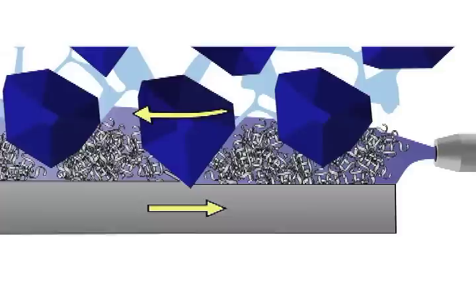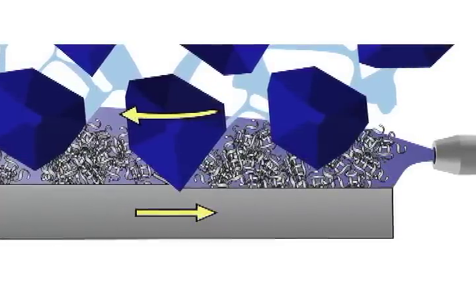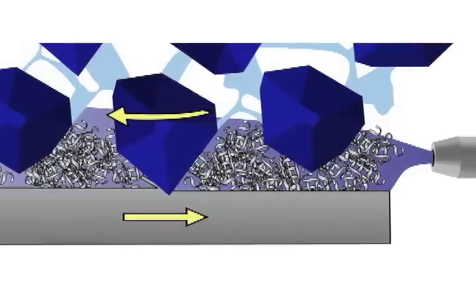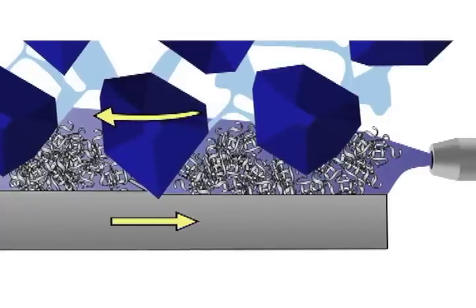Now you've got another chip coming and you have a second hot stringy chip coming and it sticks to that previous hot sticky chip. And next thing you know lots and lots of hot sticky chips stick to each other and we get a big blob of loaded material.